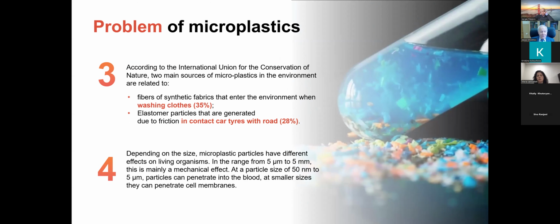Then let's go to point 4 here. It's important about this distribution of sizes. Depending on the size, microplastic particles have different effects on living organisms. In the range from 5 microns to 5 millimeters, this is mainly a mechanical effect, because these are mainly macroscopic particles. At a particle size from 50 nanometers to 5 microns, particles can in principle penetrate from the stomach to the blood, to the other organelles, and at smaller size then can penetrate cell membranes.